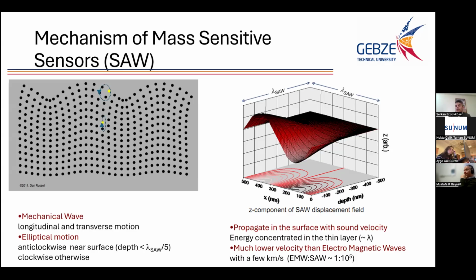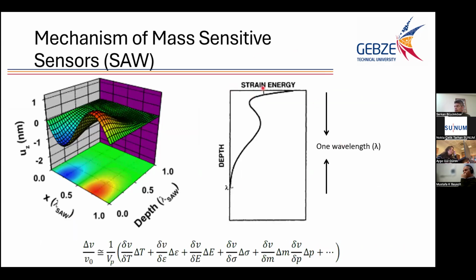For the answer, let's look at the depth and strain profile, the acoustic field or acoustic energy profile of the surface. Here, what you see is the strain energy or acoustic field versus depth profile. As you see, most of the acoustic energy is restricted to the very close vicinity of the surface. It disappears in almost one wavelength. For example, if the wavelength of the acoustic wave is, let's say, 2 micrometers, then within 2 micrometers depth, all the energy is constricted.